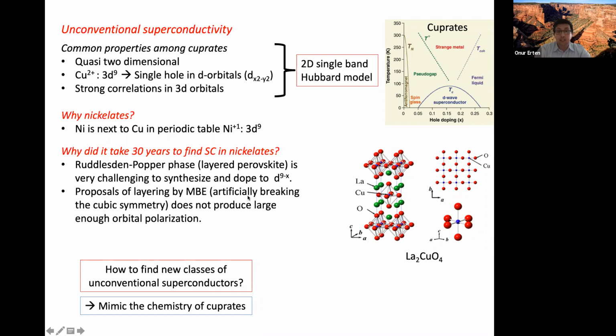But these theoretical predictions unfortunately didn't hold experimentally, because it doesn't produce large enough orbital polarization, meaning that you want really a single band. You don't want the other eg orbital. You want only the x squared minus y squared orbital. So this is why this mainly straightforward way of mimicking cuprates by using nickelates has been challenging for finding superconductivity.